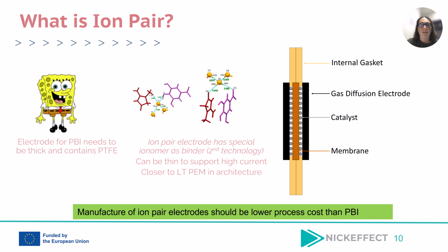The electrode for PBI today, because of this relatively liquid phosphate, has to be thick, and it contains Teflon to guarantee that the acid does not come out of the electrode. This is one of the reasons why we can only operate at low currents for the PBI product. On the other hand, the ion pair electrode has a special ionomer binder, not PTFE, but something that's a lot closer to binders used in low temperature PEM technology. Thus, we can make very thin layers of the electrode, and that's really what allows us to support high current operations. Again, closer to low temperature PEM architecture with the ability to run at higher temperatures. Lastly, the manufacturing of the ion pair electrodes should actually be a lower cost process than the current PBI electrodes.